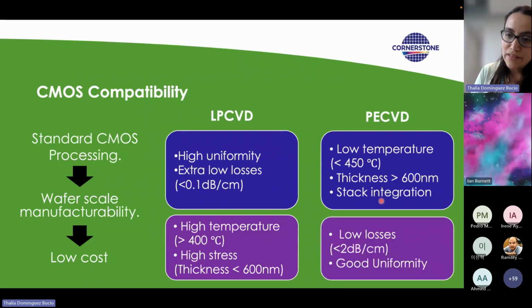And the disadvantage of PECVD is that although it gives you very good stackability and very good properties for multi-layer integration, it still has higher losses than LPCVD. They are typically below 2 dB per centimeter, but not as low as the ones that you can achieve with LPCVD. And you just get a good uniformity, not as good as with LPCVD silicon nitride.